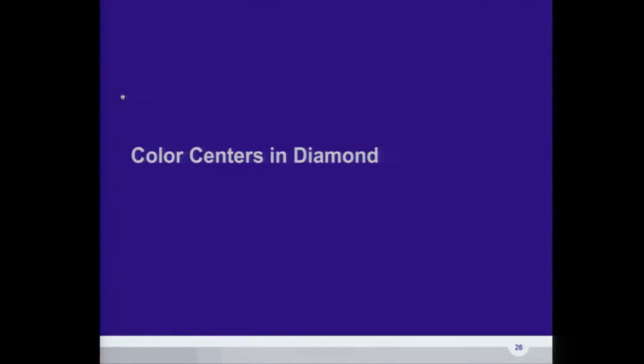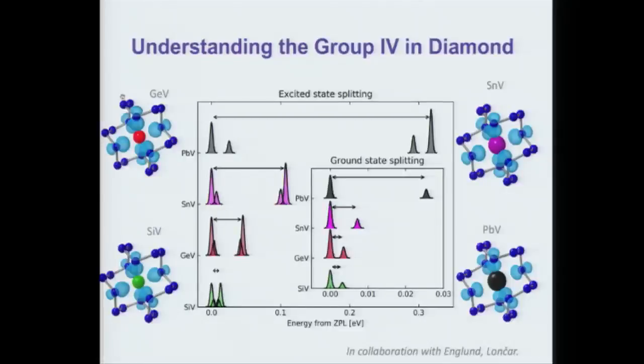With that, I will transition topics a little bit. Everything I've told you about so far has been defect-free, right? But we know that when you involve defects, things tend to have interesting properties, in particular if you can use those defects to become emitters. And this is work in collaboration with two of the CIQM PIs, Dirk Englund and Marko Loncar, where we're looking to understand color centers in diamond, in particular thinking about going beyond the NV center to other types of defects, in particular the silicon and the germanium.